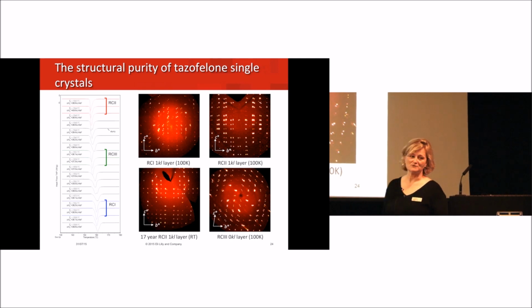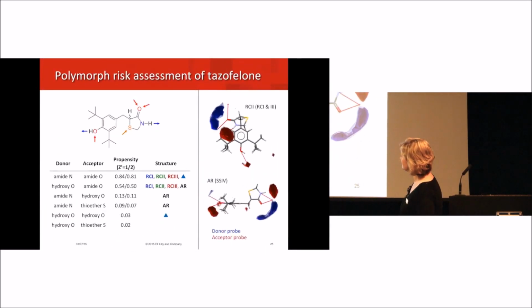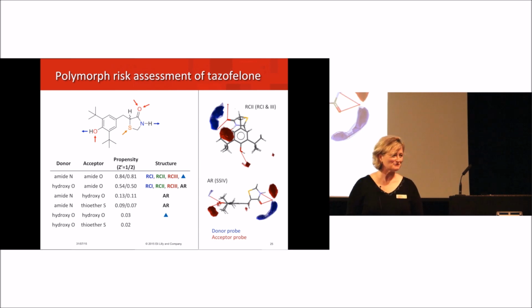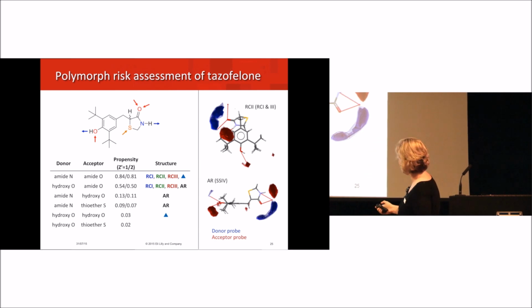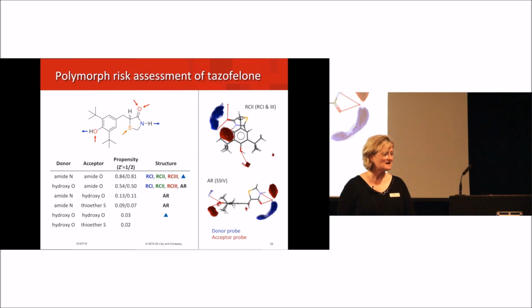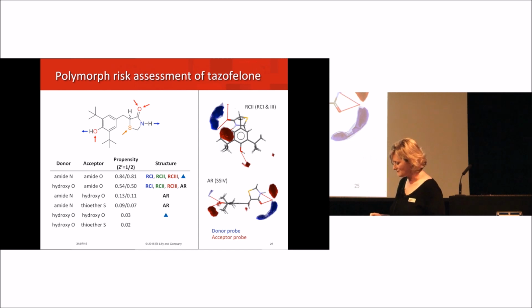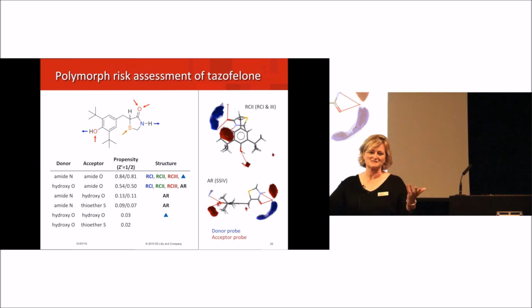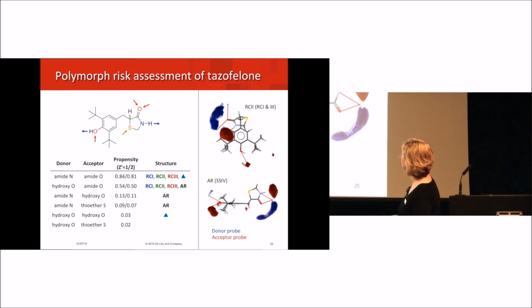But how did tazofelone fare with respect to the informatics? How does that factor into this? We did an analysis of the hydrogen bond propensity, and I would say generally it looked pretty good because we were able to show, relative to what we knew the stability to be, that the racemic polymorphs tended to have higher propensity hydrogen bonds than the less stable single enantiomer. And we could also, because we coupled this with crystal structure prediction, roll in the predicted packings into this analysis as well. One of the limitations, however, and I know Joel and others have pointed this out, is that when your hydrogen bonding is conserved among your polymorphs, obviously you can't tell the difference in the hydrogen bond propensity.